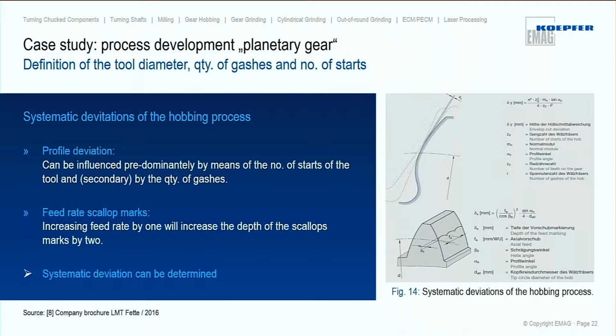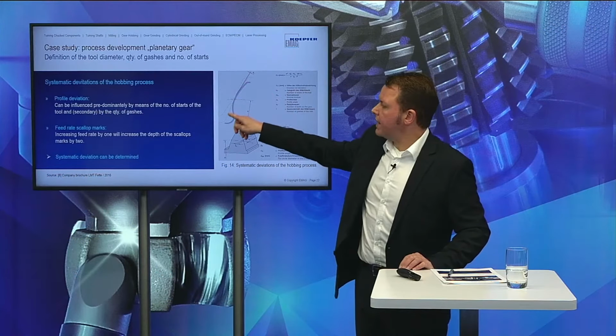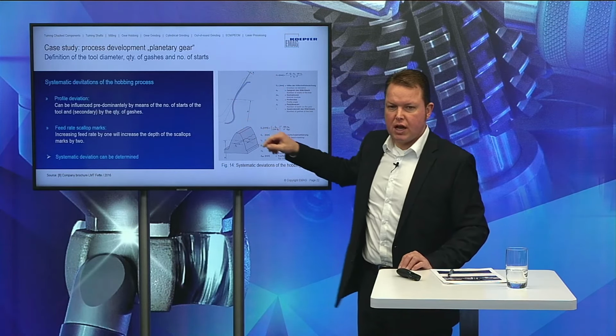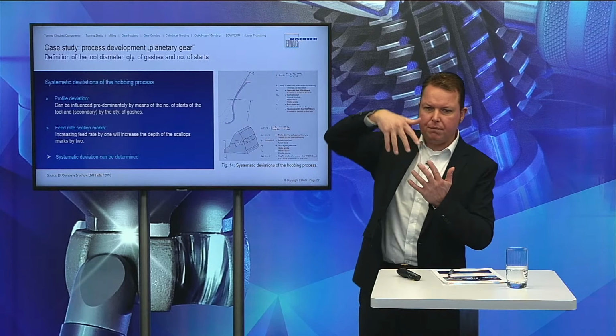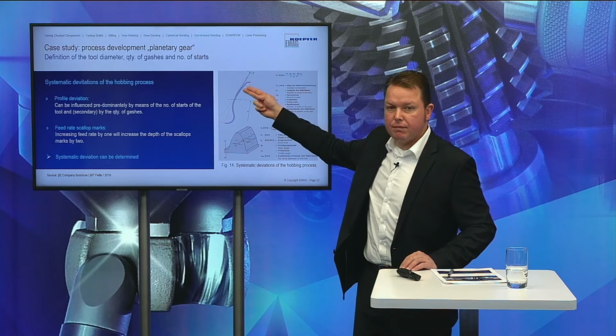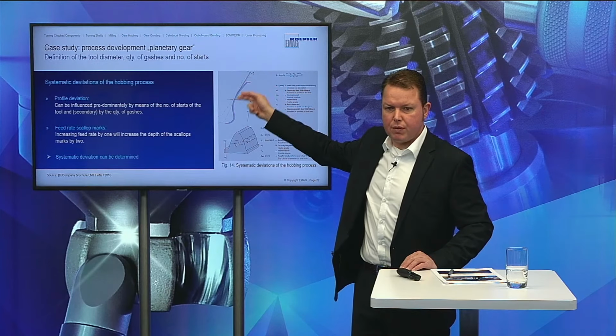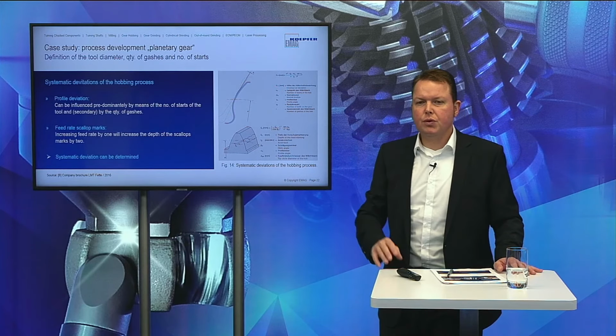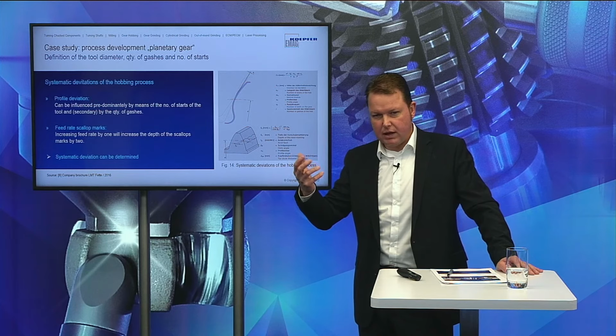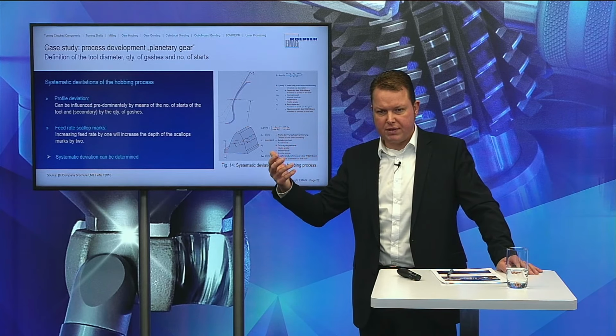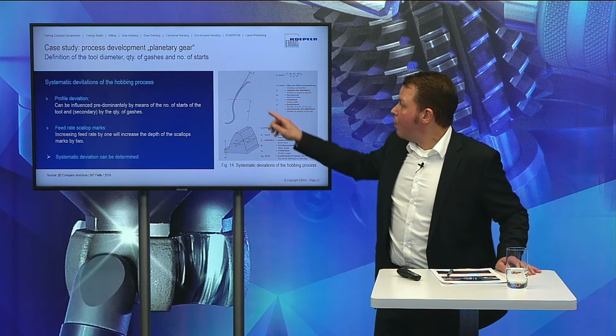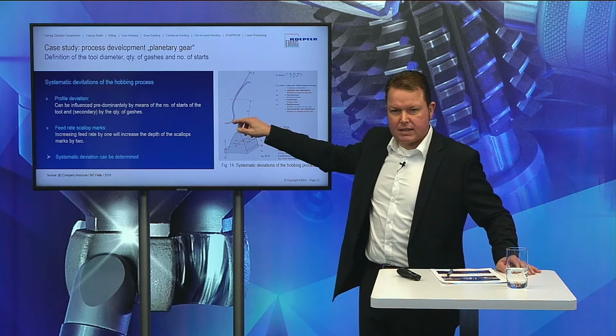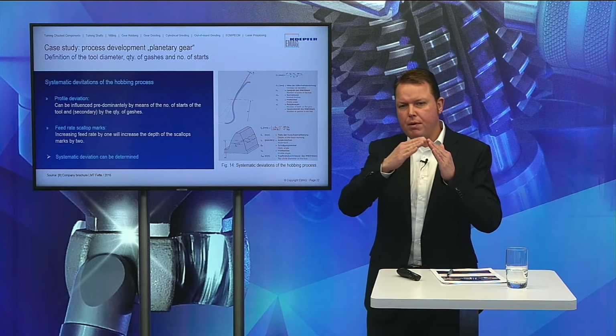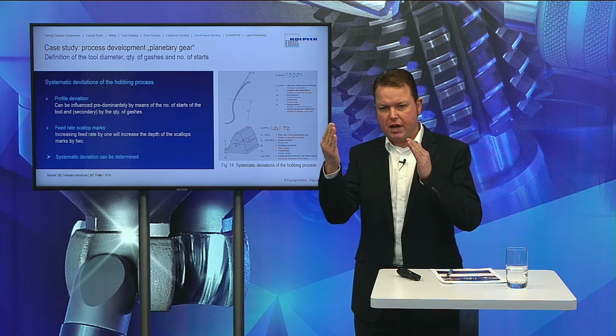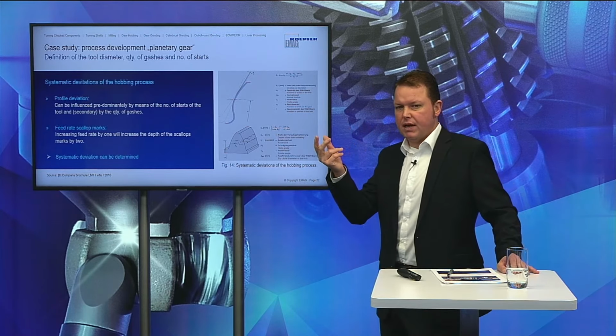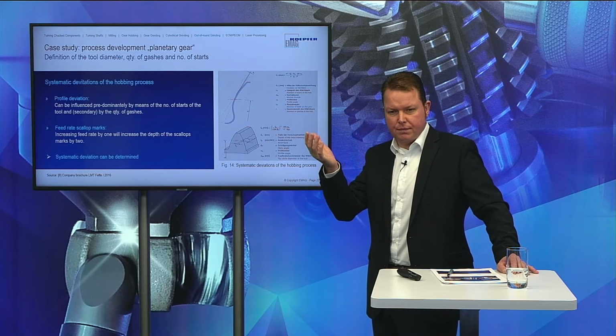When we do gear hobbing, we have a basic rack that has a straight cutting edge, and by means of the kinematics of the process, we create an involute tooth by means of this straight basic rack. And due to the reason that it is an interrupted cut and no grinding, no continuous generating grinding, but an interrupted cut, we will create this by individual cuts. And so it's actually not a real perfect involute, it is a polygon shape. And there we have systematic deviations, and we can influence them by the design of the hob.